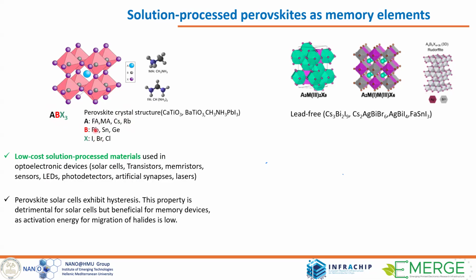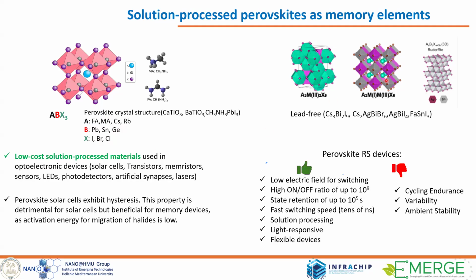On the B side, we have mainly lead. It's the best performing material, but we have issues with the toxicity. Even the same with tin. And also germanium is used, and the X side is the halides, iodine, bromine, and chloride that have been used. On the right, we have some lead-free approaches that we also use in our lab.